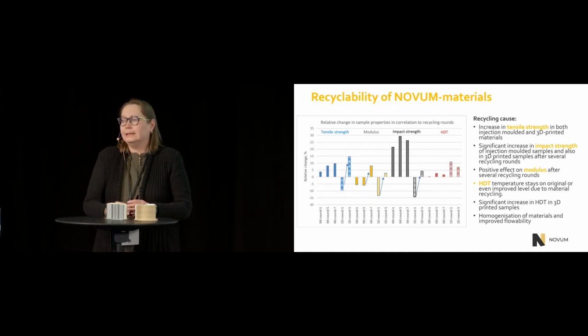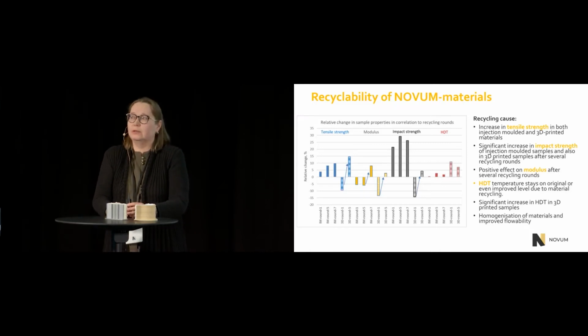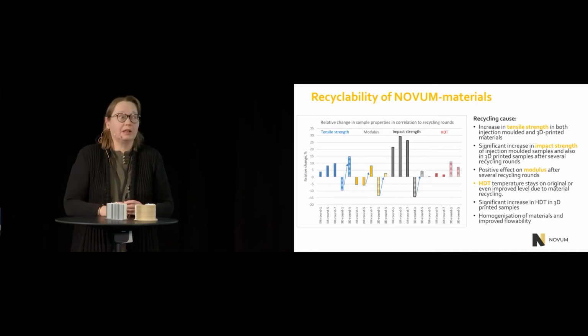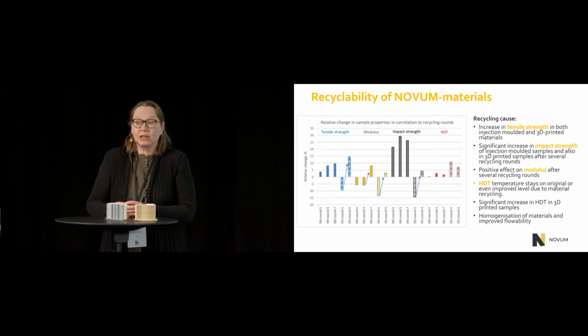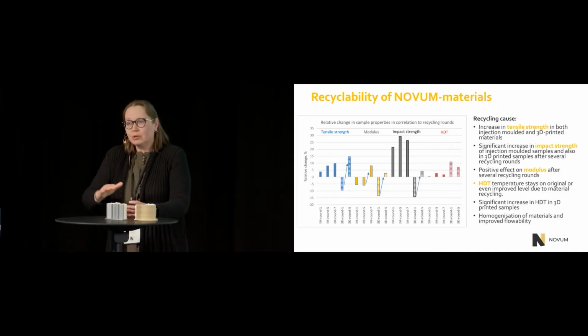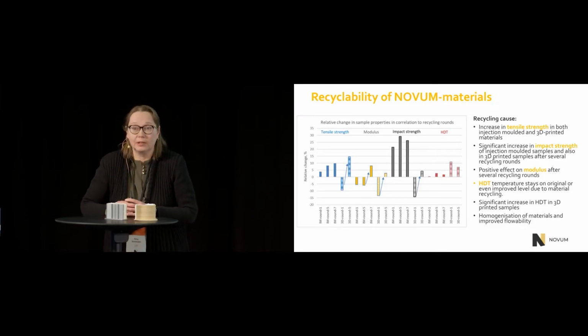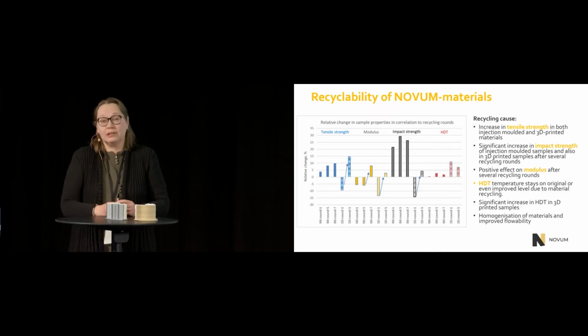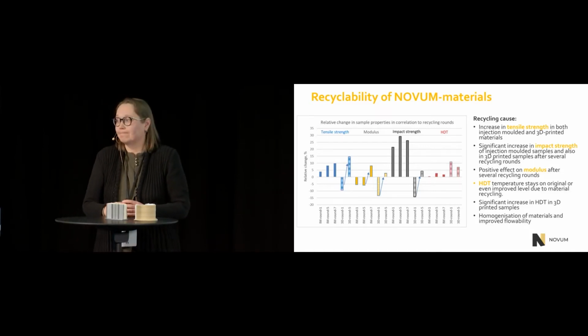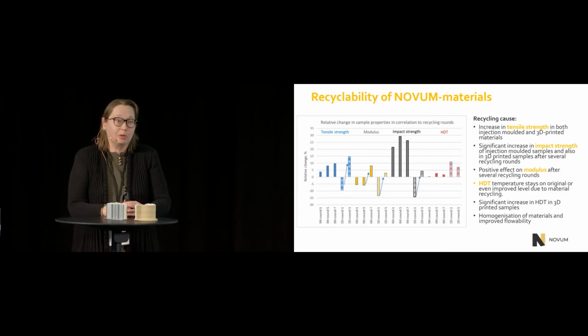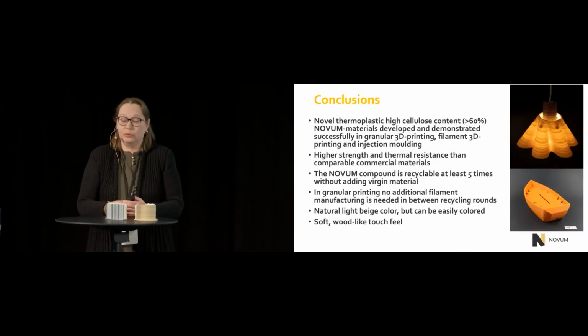Then if we take a closer look at the recyclability, you can see here the relative change that recycling causes. There's an increase in tensile strength properties and impact strength properties. Modulus stays at a little bit the same level, with a small increase in HDT. And we can say that the more you recycle the material, the better properties you get, at least with the injection molded materials. This is mainly due to the homogenization of the material and improved flowability.